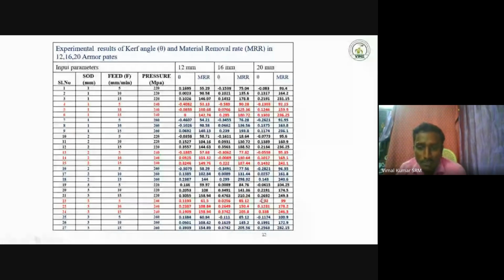So in this condition, for the 20 mm plates also, the input parameters are different. Not only for the same materials, but for different thicknesses also, the input parameters change in the abrasive water jet machine. The material removal rate also changes, because whatever input we give, the material removal is based on that input. We give the input values of the measurement using ImageJ software, and we get a different material removal rate for each trial. I hope you understand that these are the input parameters for the three thicknesses of material, and we will get three different values of kerf angle and material removal rate.